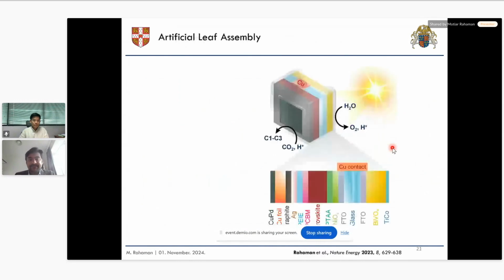artificial leaf device? We need two different light absorbers. For the photoanode, we use nanostructured bismuth vanadate. We added a titanium cobalt water oxidation catalyst on top of it. So that photoanode converts water into oxygen. On the other side,